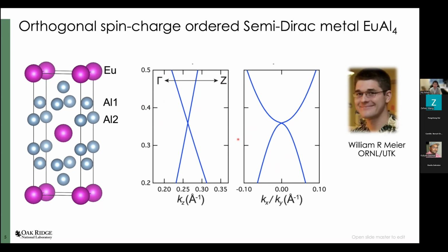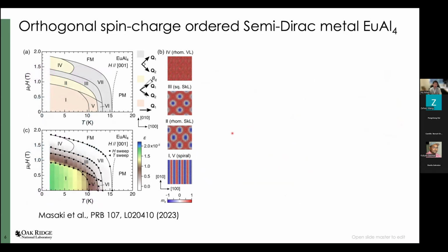But of course, we are interested in this material not only because of this topological electronic band structure, but more because of its fruitful phase diagram. Here I show the low temperature phase diagram. The vertical axis is the magnetic field and the horizontal axis is the temperature. You see there are a lot of phases, not too surprising for a rare earth metal, but part of the interest is because there is a large region where people believe it forms a skyrmion phase. The skyrmion is quite small, and people are debating what drives it, maybe RKKY or some other mechanism.